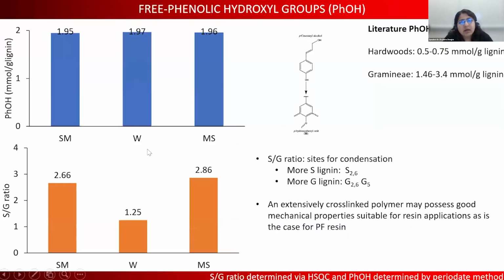We also characterized the lignin for several other of its properties. One of the key properties of lignin is the free phenolic hydroxyl groups, which determine the reactivity of the lignin. As you can see, all three lignins showcase a similar free phenolic hydroxyl group content, about 2 millimole PhOH per gram of lignin. This is slightly higher than what you would see in literature based on milled wood lignin values, where the lignin is much more preserved, whereas in the hot water extracted lignin, you're seeing some degradation that occurs during the extraction process.